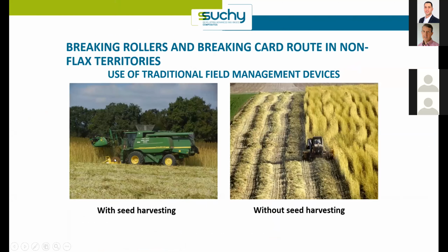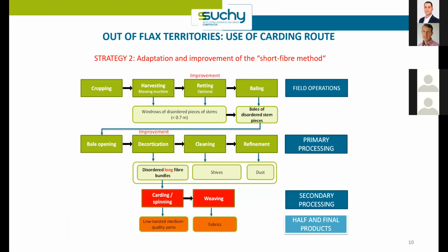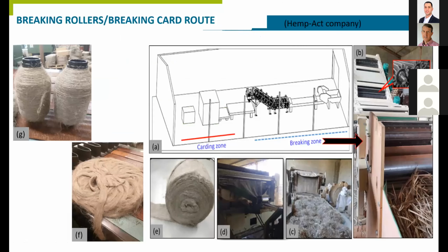So, for example, in places where hemp is also harvested for seeds, or when it's not harvested for seeds, but when it's not possible to harvest it by machine laying down the stems, and when the stems are randomly aligned, like you can see on the picture. In this case, the strategy was to adapt and improve what is normally called the short fiber method, or the tow approach, tow method. So once again, with also field operation, primary and secondary processing. So I try to be a little bit quick in there.